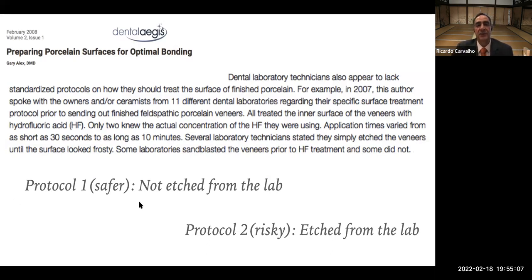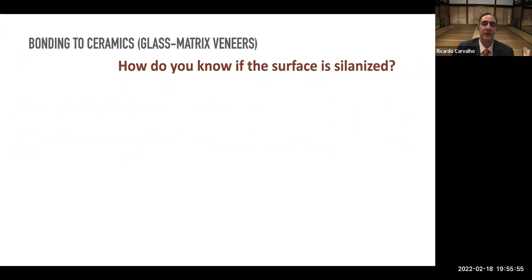So the safer protocol for you is, if you have a chance, ask the laboratory just to send the veneers to you. Do not etch in the lab, because if you etch in the lab, until it reaches your hands in your practice, there is a huge time frame in which the surface can be contaminated. And when you are handling your veneers in your practice, if they're etched, you have to be careful not to contaminate them with any oily surfaces, with any powder from the gloves, or anything else, including the try-in paste, which is a contaminant and should always only be used after you silanize. So if it comes etched from the lab, be careful. Ideally, you should do it yourself chairside before you are bonding any of your ceramics.